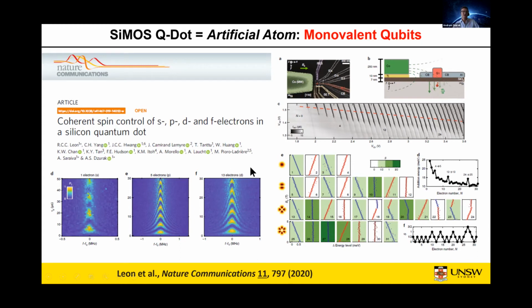And what Ross showed in this beautiful paper is that when we are in the single valence states, so with 1 electron, or with 5 electrons, when we have a single P electron occupied, or in 13 electrons with a single D electron occupied, we can observe excellent Rabi oscillations and very, very good coherence as well. And so what this means is that we can operate at higher electron numbers, which screens out disorder, and we don't have to worry about operating at this very low 1 electron limit. So it's a very, very important paper for us.